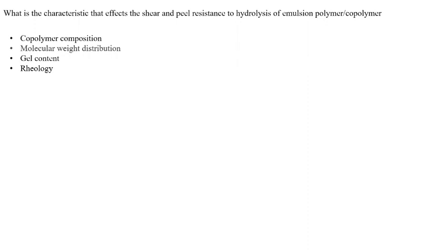And one of the best ways to make a stable polymer is to have a sufficiently high molecular weight distribution. If there is a high molecular weight distribution, since it is very high, it will have longer chains and larger entanglements, and because of that the shear and peel resistance will increase. So that's why molecular weight distribution affects the shear and peel resistance of hydrolysis of the emulsion polymer.